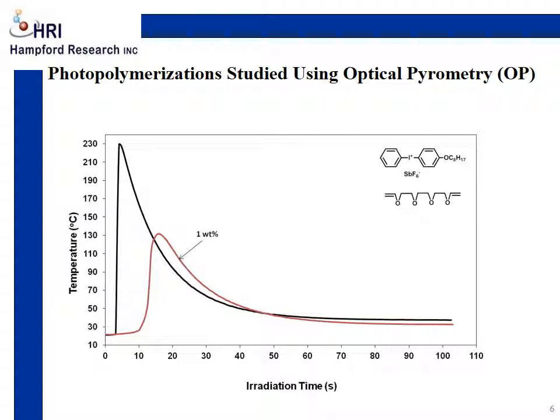You can see this through simple OP kinetic analysis. In this analysis, samples were prepared by sandwiching a thin film of liquid monomer containing the designated photoinitiator between two plastic sheets. The average thickness of the sample was 0.9 millimeters. Irradiation with UV light was carried out using a mercury arc lamp equipped with a liquid optic cable. A minimum of 3 kinetic runs were performed for each system to ensure reproducibility, and the temperature of the sample was monitored at a rate of 2 measurements per second.